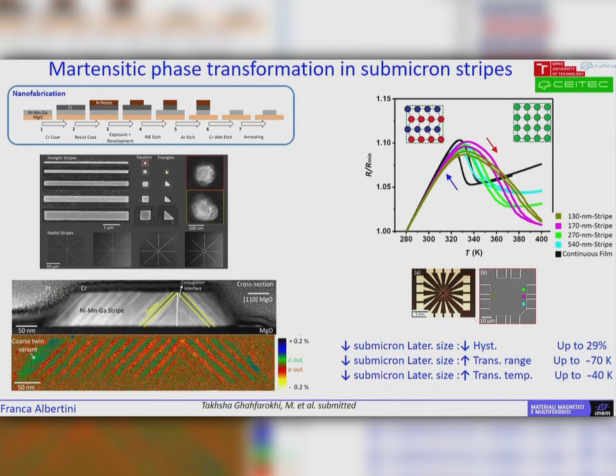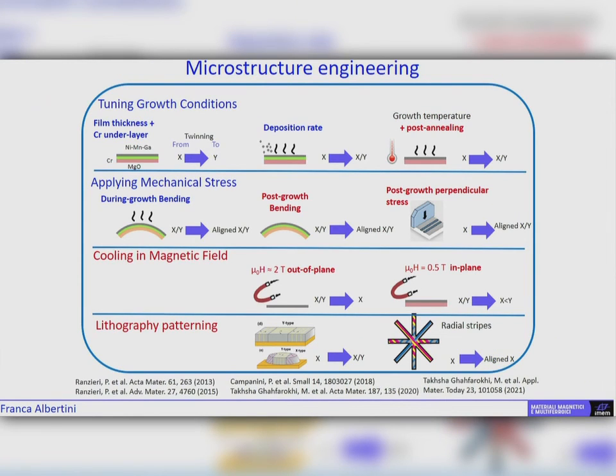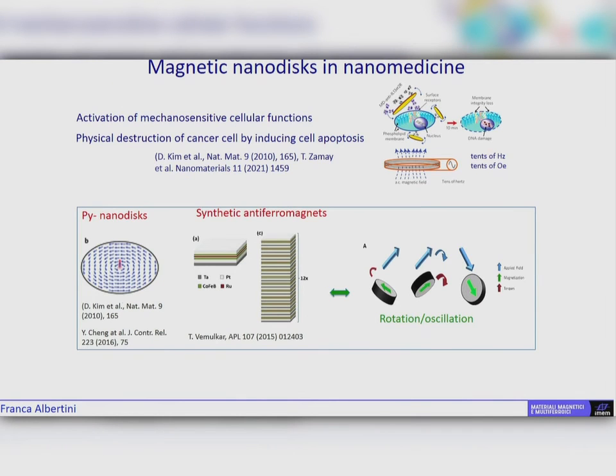Here we are now making some model, and we have involved some groups because we have to take into account many aspects, including surface energy of these materials, and we try to model the effect of all the terms in this behavior. So we have seen also the effect of lithography patterning. So we change microstructure, and we can also select a kind of microstructure by geometry. And lastly, I show you some results that we have obtained, but this is a direction that is interesting for us, and this topic has inspired our idea to detach the ferromagnetic shape memory thin films from the substrate. And the idea is to have materials that can be used for some cancer therapy,